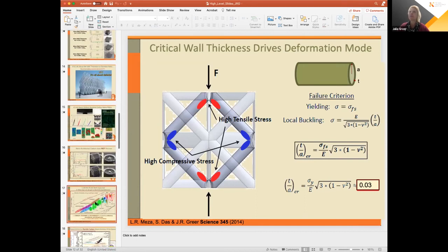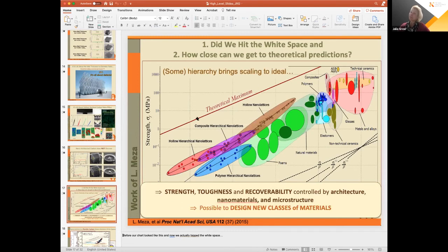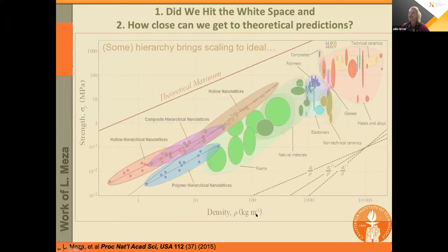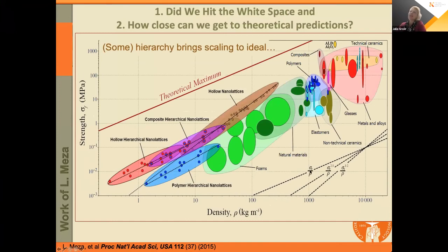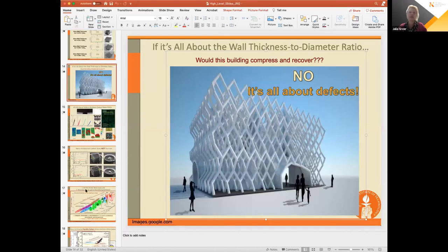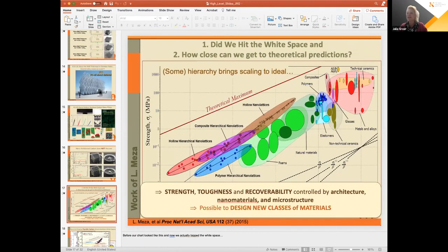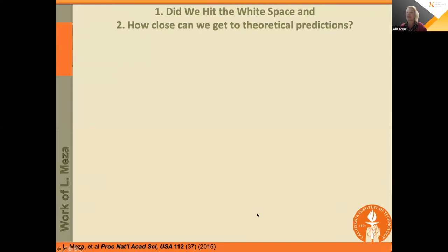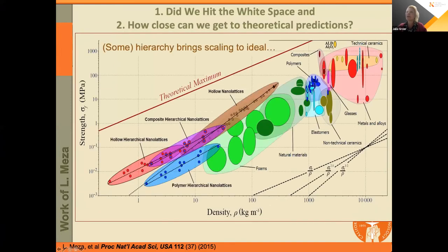For example, when I showed this plot, you can see that the slope here is linear. Let me go to full presentation mode. When your material is so-called stretching dominated, you should see this linear scaling between the strength or stiffness and the reduction in density. This is what I meant to show you. But what you see here is that it's less than ideal, and that's because of this damage initiation. So what you can see in the slope in our nanolattices, at least in the ones that don't have any hierarchy built into them, is that the slope is less than ideal. It's specifically because of these local deformations and possibly microcrack formation and the local processes that are not recoverable.